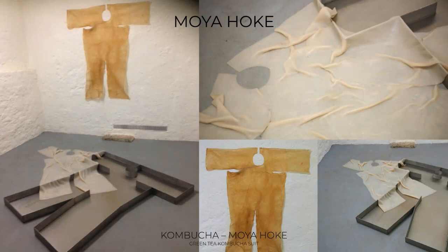Another very important thing to think about is actually the general temperature with which kombucha grows, which is between 25 and 30 degrees at its best. Meaning that if you have a stable 30 degrees, it might grow within a week. But when you work at lower temperatures, such as us here in Amsterdam, for example, it might take up to 1 or 2 months. So it will keep growing, but it will just go a little bit slower. What you can do is, of course, put it next to a heater, or grow it in bain-marie with heated water around it.